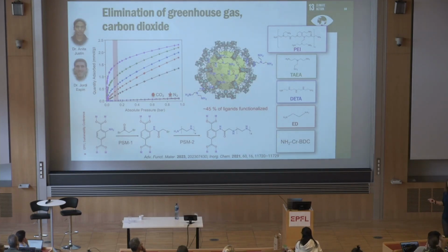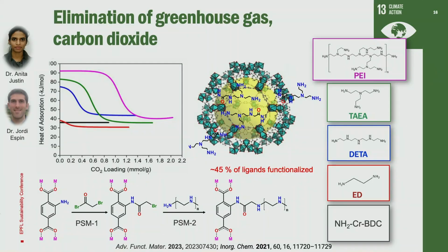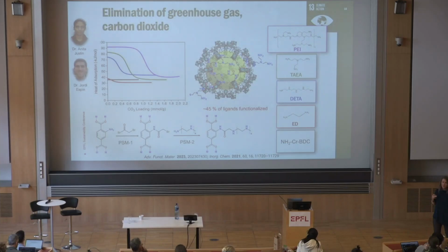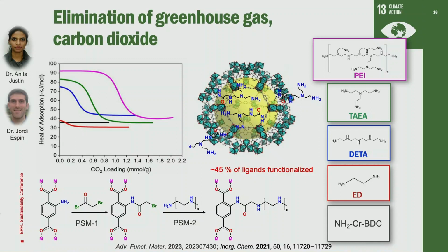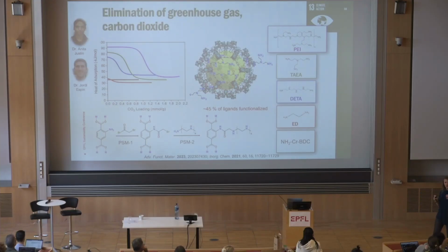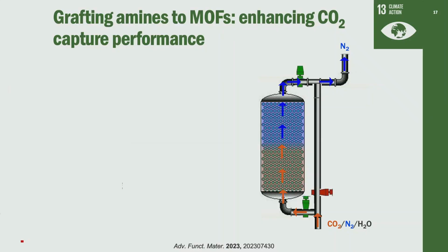You see that the nitrogen is really not being taken up inside the material, okay? So as a result, we can calculate our selectivities. It is over 400 times more selective for CO2 than it is over nitrogen. Nitrogen is important because it is the most concentrated element inside the gas stream, okay? So here you can see the binding energy may not make a difference to you guys, but 90 kilojoules per mole is quite strong. This is what tells us that our amine is reacting with our CO2. This is not just a weak interaction. So from what I've told you so far, I've only shown you a single component.